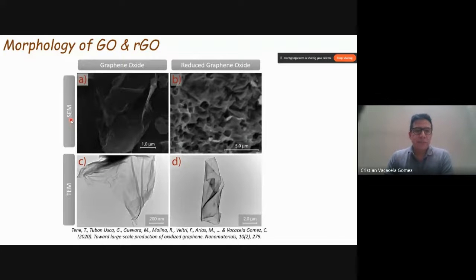Look at here, for example, we're using the scanning electron microscope in picture A and picture B. So we have graphene oxide and reduced graphene oxide. First, after the oxidation process with all the chemical agents commented before, we can see a corrugated structure, so several damages in the plane and at the edges. And after the reduction, more or less, we can identify by using the scanning electron microscope a regular structure, and also the generation of different mesopores or micropores in our systems.